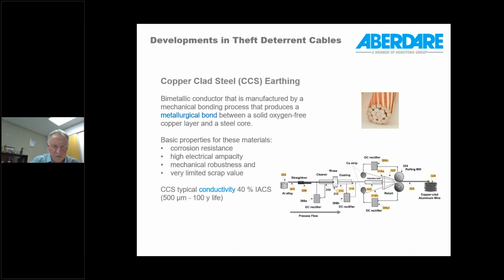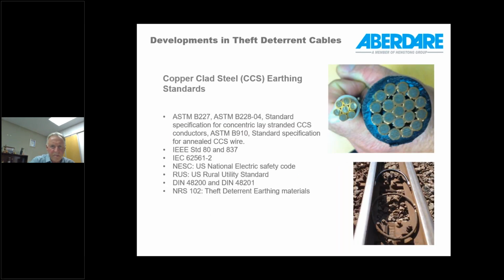So normally, or generally, the most common conductivity for copper-clad steel is 40% IACS, which is 40% of the copper conductivity standard, and where a 500 micrometer thick layer of copper relates to a 100-year life for this metal. So it's good to be installed underground, buried directly as well.